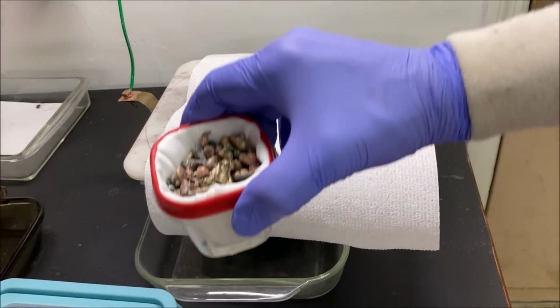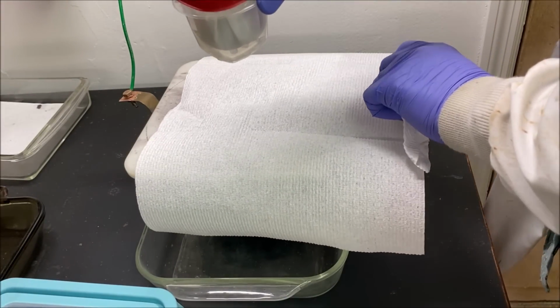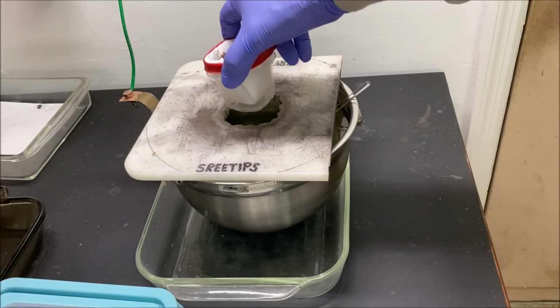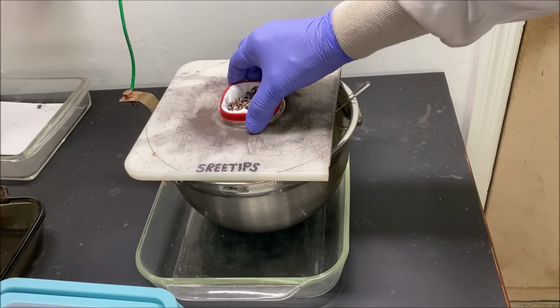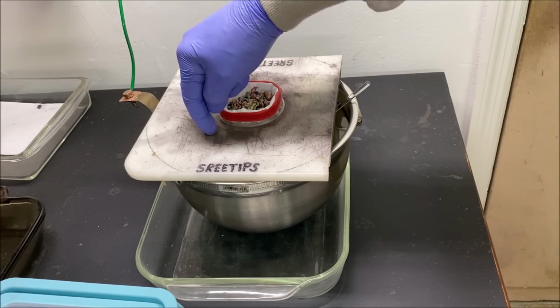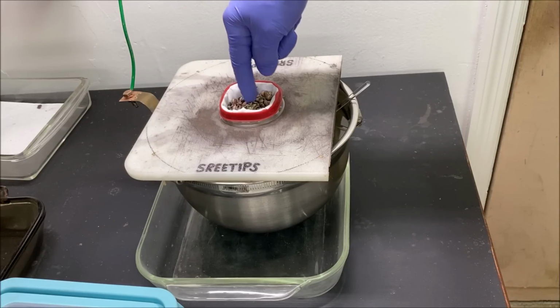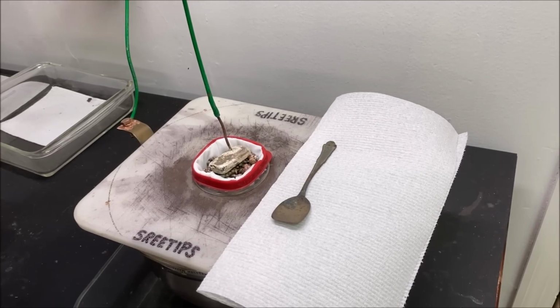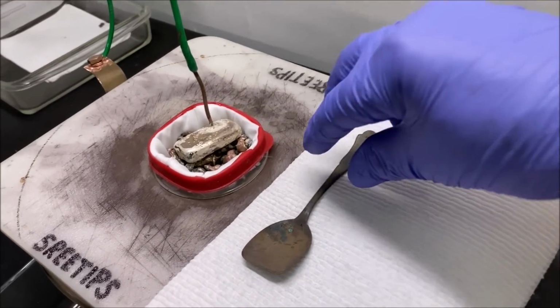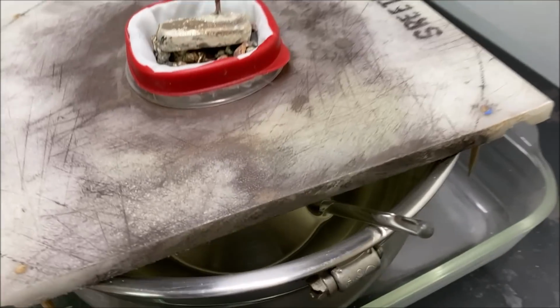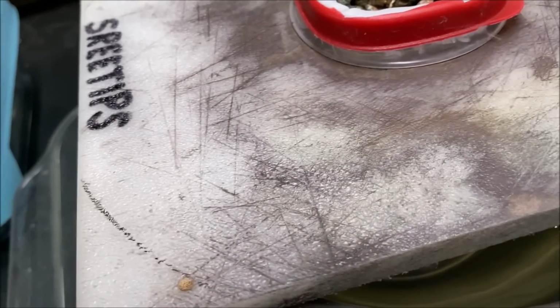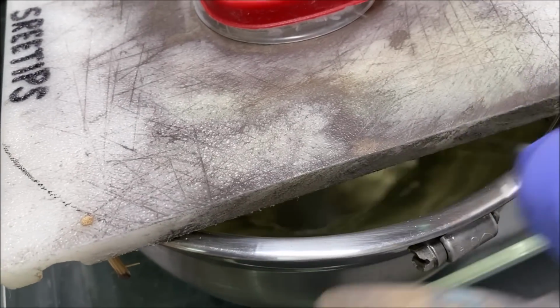Now what we'll do is drop our anode basket down into the electrolyte. The bottom of it will be submerged in the electrolyte and make contact with the impure silver that's in this anode filter. I've got the silver cell all configured now. This is our electrolyte down in a stainless steel bowl. And I've got a stirring rod that I use to stir this up.